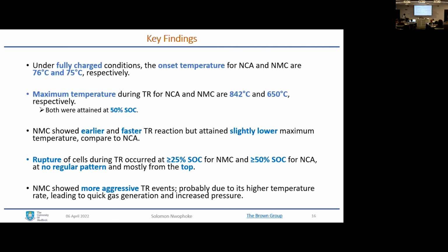And here we observe that under fully charged condition, which represents the worst case scenario when the battery contains the highest amount of energy if it is used as directed by the manufacturers, that is excluding the case of overcharge, the onset temperature for NCA is 76 degrees Celsius and 75 for the NMC. The maximum temperature during thermal runaway for NCA is 842 degrees Celsius and 654 for NMC. Sorry, 842 degrees Celsius for NCA and 650 degrees Celsius for NMC.